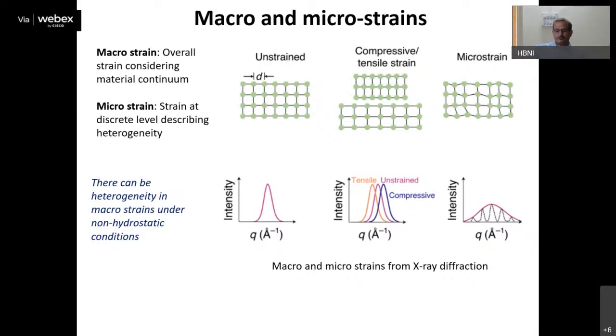This is an example of macro strain. Whereas if there are some defects or some impurity in the system, locally there may be different ordering close to the atoms. In this case, you cannot see it, but this will have different strains. So if you define your strain tensor very locally, you will get this difference in strain components. You call it microstrains because experimentally, what you are looking at is the fluctuation in the strain about this macro strain.